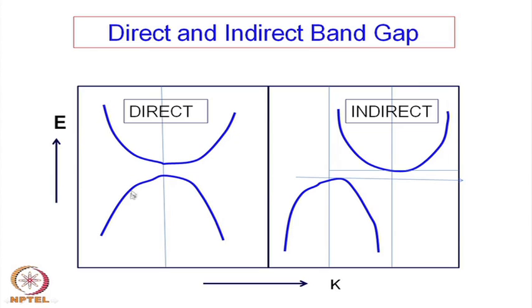It can start there and follow an inclined path as well, but generally the vertical direction is shown here, and the minimum gap is the forbidden energy gap. Always we have to remember this is the minimum energy gap. So, if a particular solid has two different Brillouin zones of this nature and we have to say what the band gap is, then we have to draw this gap.